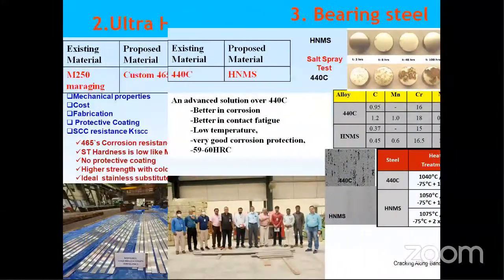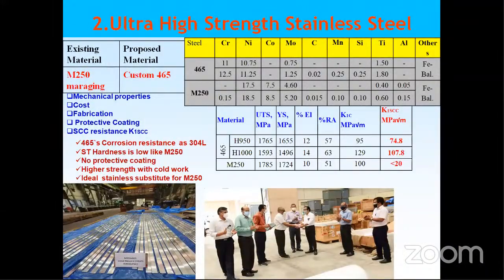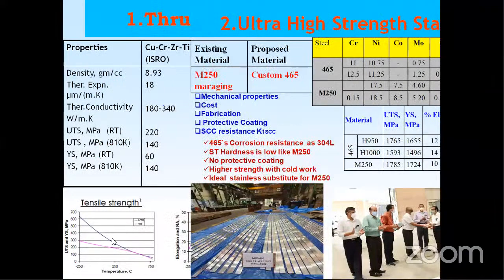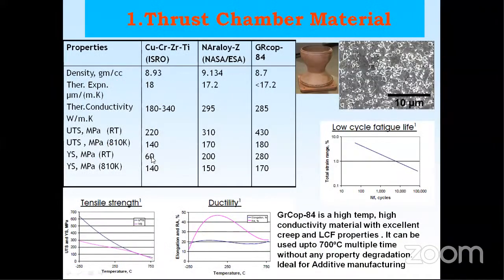Just a minute. Whenever I'm forming this alloy, my yield strength is only 60 MPa. But at high temperature, it increases. We don't see such a thing in other materials. At ambient temperature, this YS value is low, but at high temperature it is high. This is a very interesting thing.